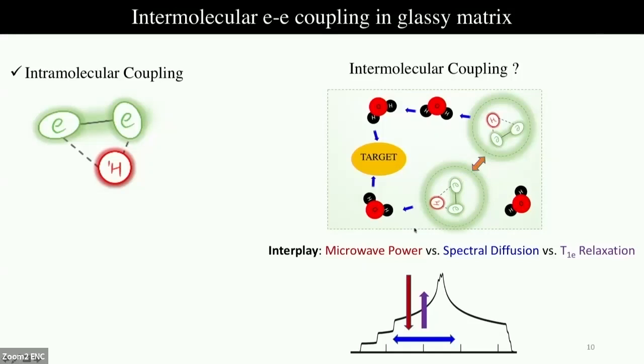In general, we always have an interplay of microwave power, which leads to saturation of the electron spins, and then we have spectral diffusion, where that saturation effect is transferred across the EPR spectrum. And we also have relaxation of electrons. So it's the interplay of these parameters that determines whether or not the DNP would be efficient. It's hard to monitor the effect of spectral diffusion if we are working with a nitroxide kind of radical, because the EPR line is very broad and all the different DNP mechanisms overlap. But it's possible to make use of a narrow line radical and see the effect of intermolecular coupling.